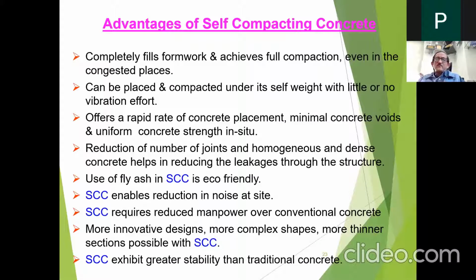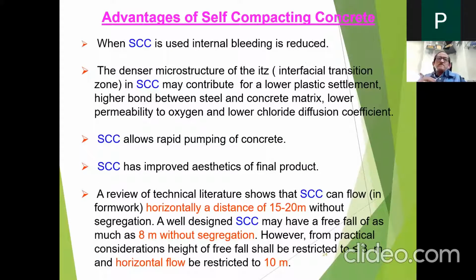Then SCC requires reduced manpower, more innovative designs, more complex shapes, more thinner sections possible with self-compacting concrete. SCC exhibits greater stability than traditional concrete. When SCC is used, internal bleeding is reduced because you have got a very good rheology of the concrete. The denser microstructure of the ITZ, the interfacial transition zone, in SCC may contribute to a lower plastic settlement, higher bond between steel and concrete matrix, lower permeability to oxygen, and lower chloride diffusion coefficient.